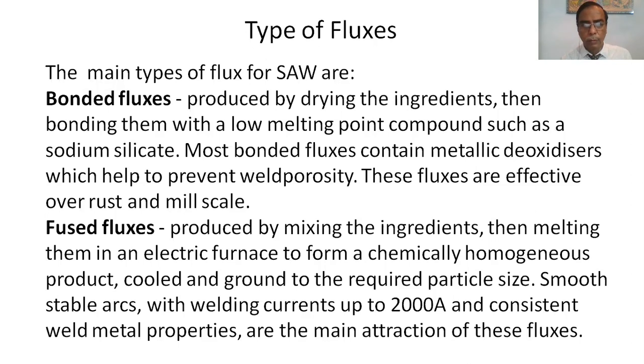Fused fluxes produced by mixing the ingredients then melting them in an electric furnace to form a chemically homogeneous product, cooled and ground to the required particle size. Smooth stable arcs with welding currents up to 2000 amperes and consistent weld metal properties are the main attraction of these fluxes.